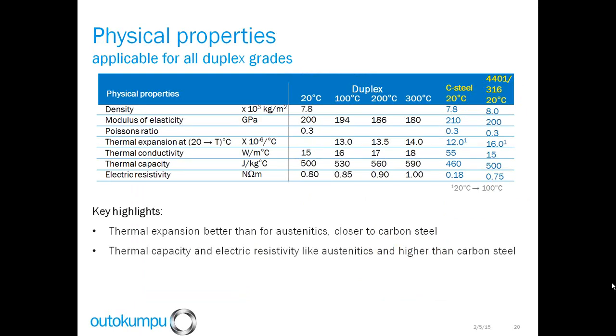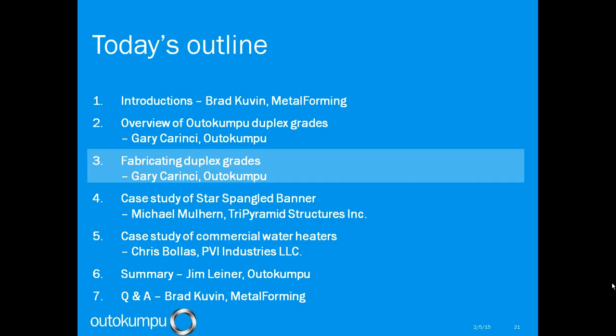Next, we have the physical properties of duplex, and here we compare duplex versus carbon steel and 316 stainless steel. This table shows the coefficient of thermal expansion of duplexes is between that of carbon steel and 316 stainless steel, and the thermal capacity and electrical resistivity are similar to austenitic stainless steel, but higher than carbon steel.